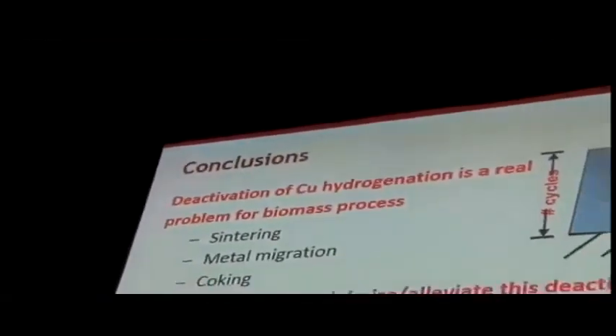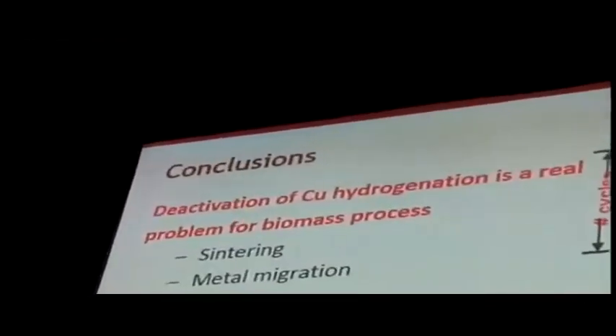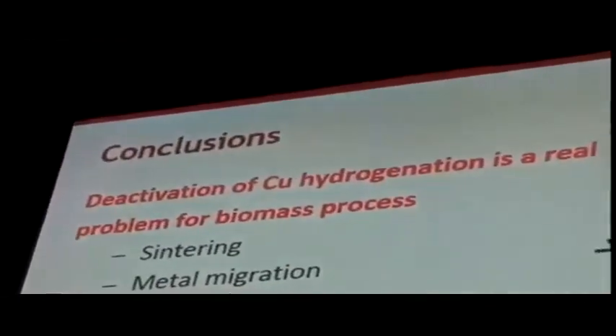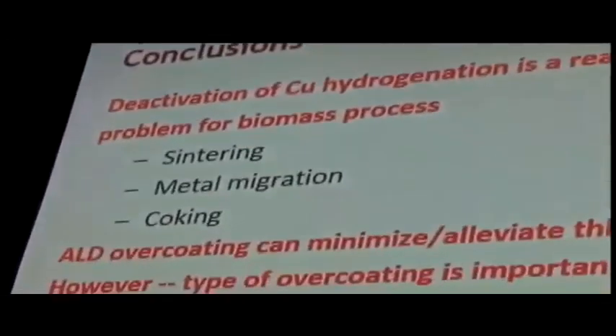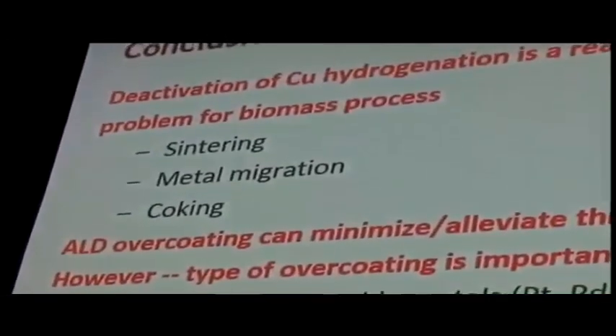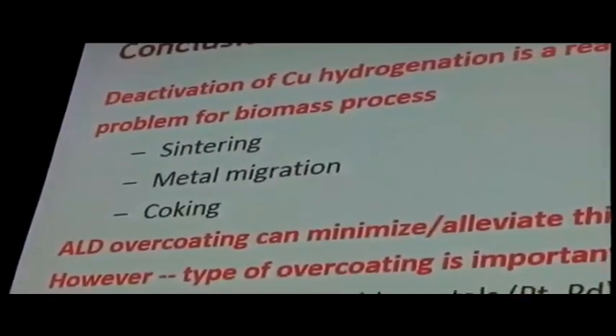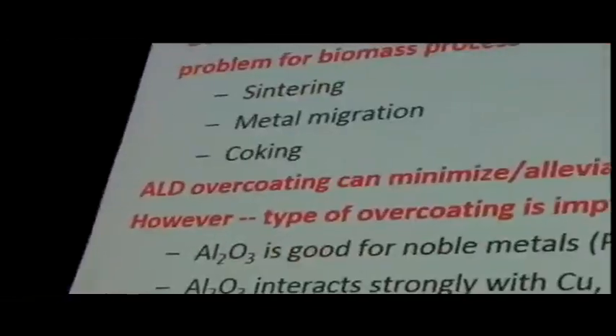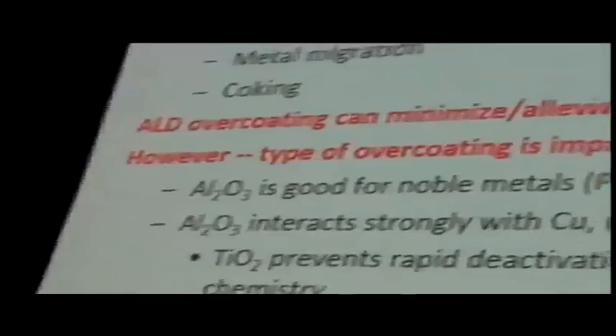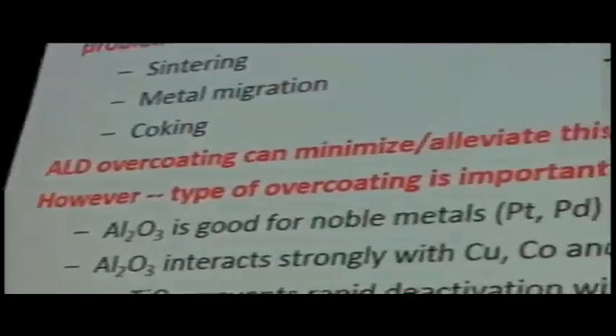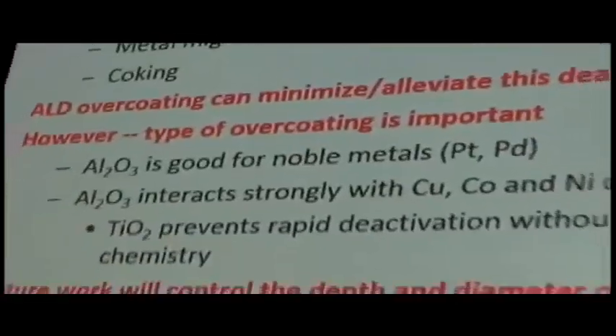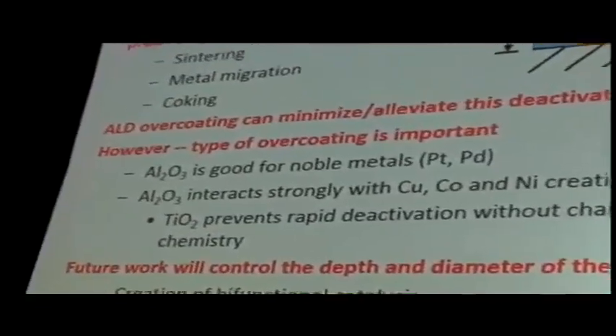So in conclusion, I've shown that the deactivation of copper hydrogenation catalysts is a real problem. We see a number of things going on. Sintering of the metal is very important, especially in high temperature liquid water. And we also see coking going on there. ALD overcoating, as we've seen in many cases, can protect those metals, but you've got to be careful as to the types of overcoatings you use.